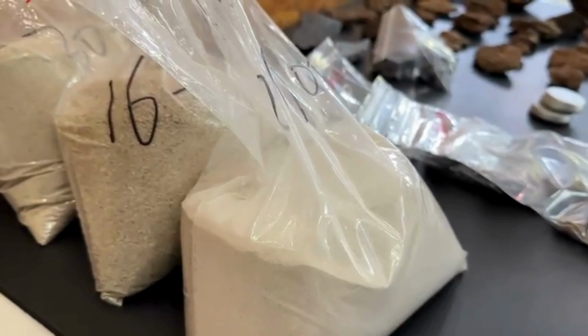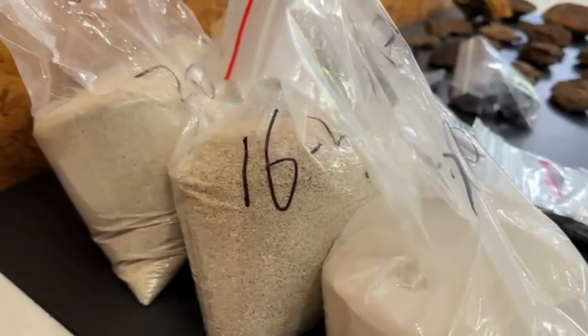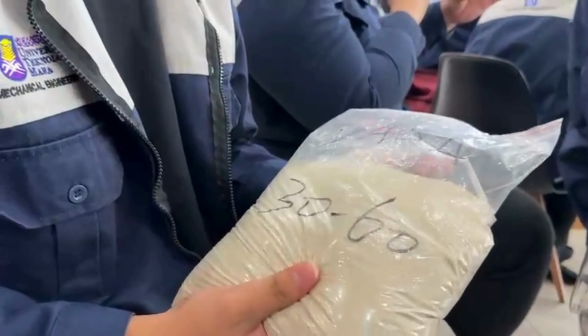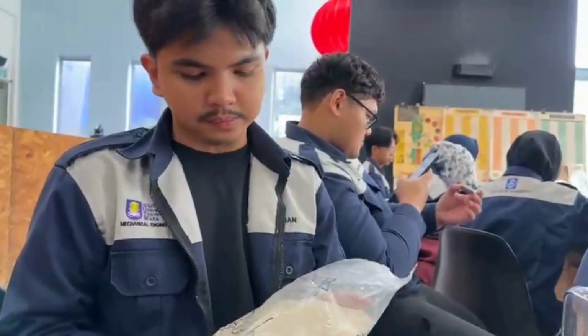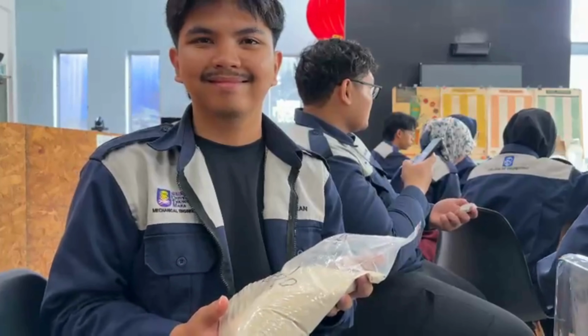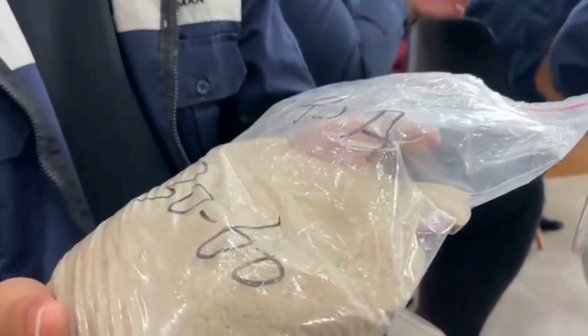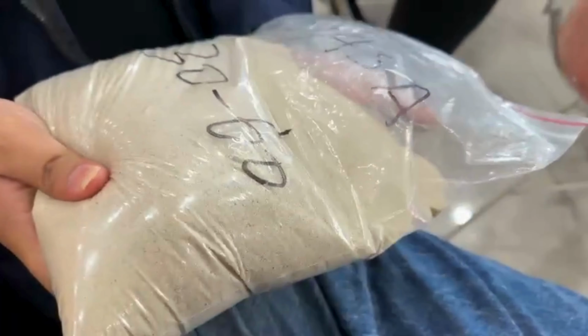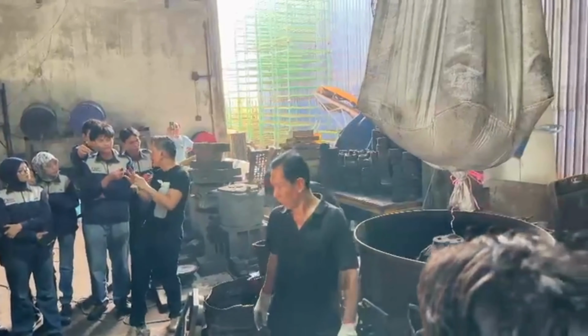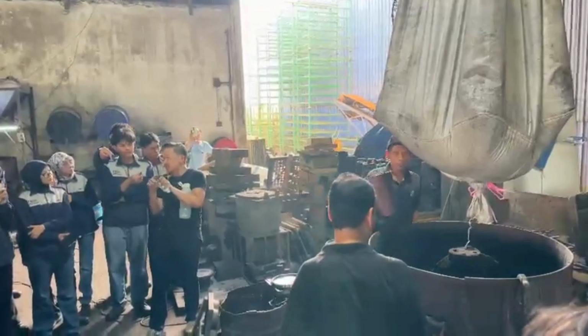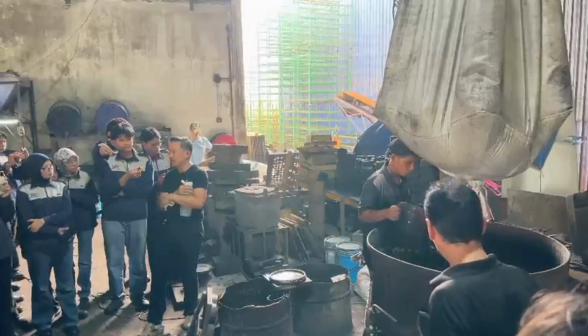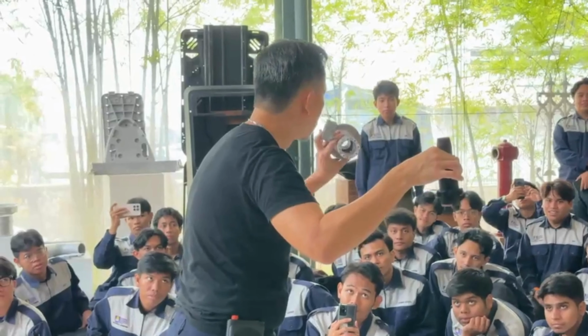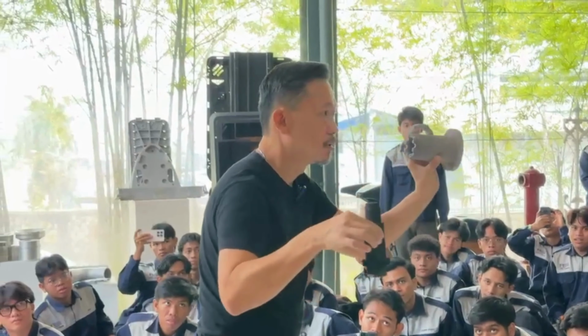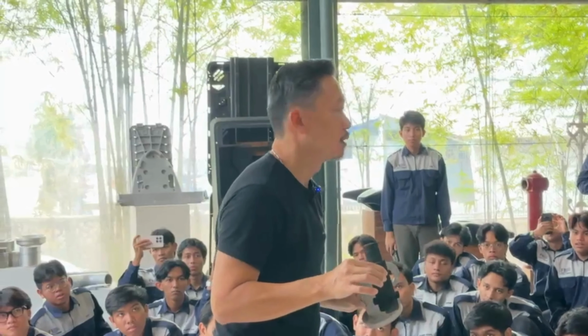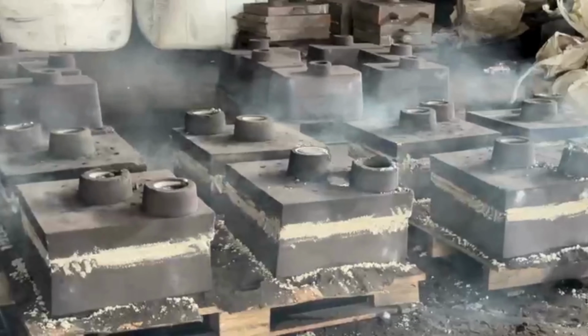To eliminate the blowhole defect, our group proposed two targeted engineering improvements. First, Sama Mahir should implement a strict moisture analyzer at the sand mixing station to ensure the water content in the green sand remains strictly between 3% and 5%. Second, we propose a redesign of the mold gating system by adding more vent holes and risers to the top half of the mold. This will provide a direct exhaust valve for steam and gases to escape before the metal hardens.